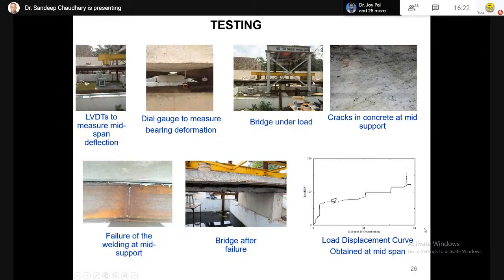There's a deflected profile. So there's so much load that the steel girder or the composite section is now showing a particular deflection. And initially we observed cracks in the concrete at the mid support. Of course, before we reached the ultimate load, there was a failure of welding at mid support. So it could have gone much further if the failure of welding had not taken place. So that means the failure was not due to epoxy here, the failure was particularly due to welding.